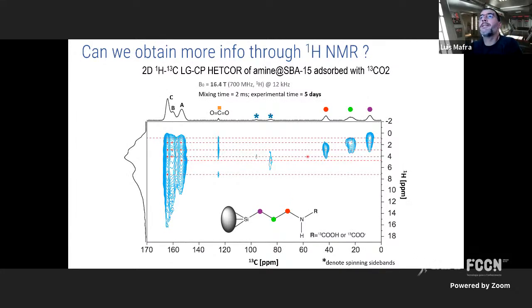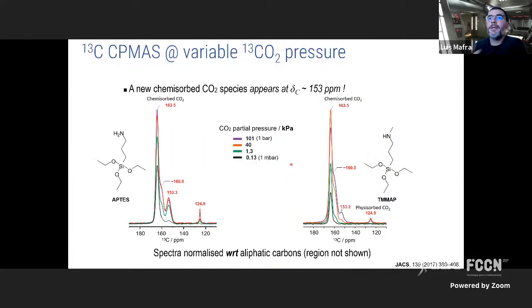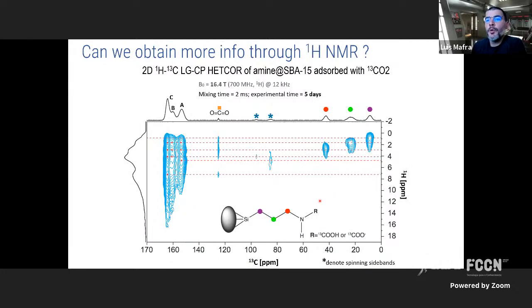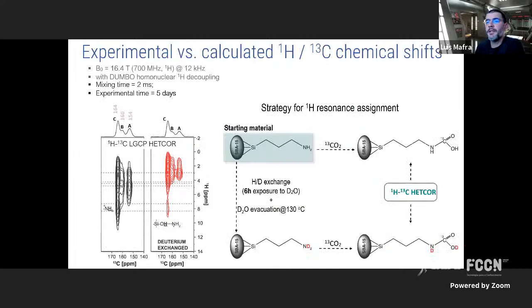So from carbon, we just see the peaks, and we have here a huge overlapping of environments, okay? What about trying to extend our vision through the unknown by playing with another dimension, this time the proton dimension, this vertical dimension? We can now see how the spins speak with each other, so how they are coupled dipolarly. If a carbon is close in space with another proton, you will see a cross peak showing in this contour plot map. So you can see that these three chemisorbed species correlate with basically the same protons, but some difference can be observed here. Okay. Still very complicated to interpret.